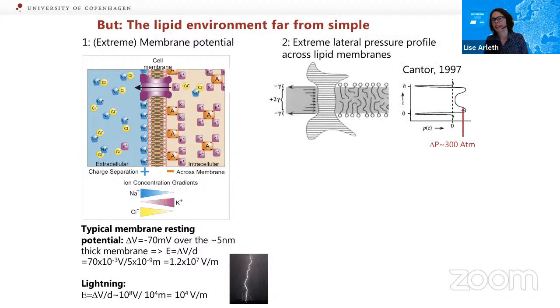Also, there's a rather extreme lateral pressure profile across the lipid membranes. This was proposed by Cantor in 1997 in a theoretical work, where he calculated that the positive pressure and the oscillations in the pressure over the membranes, between the hydrophilic head groups and hydrophobic tails, would vary by about 300 atmospheres over only these 5 nanometers. This is something that we still don't know how to measure and confirm experimentally, but there are some very convincing theoretical arguments that this should be the case. So an extreme lateral pressure profile environment also.